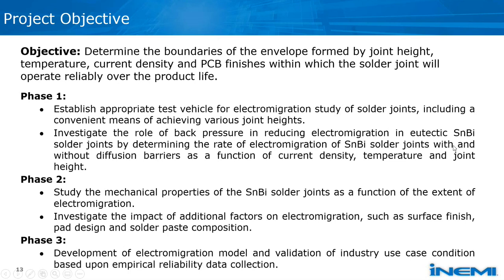This being done with the use of ENIG surface finish, which has nickel as a diffusion barrier. If the element that segregates due to electromigration is brittle, bismuth being one such element, then the reliability of the solder joint that is subjected to electromigration will be impacted by the amount of segregation happening. This effect will be studied in phase two.